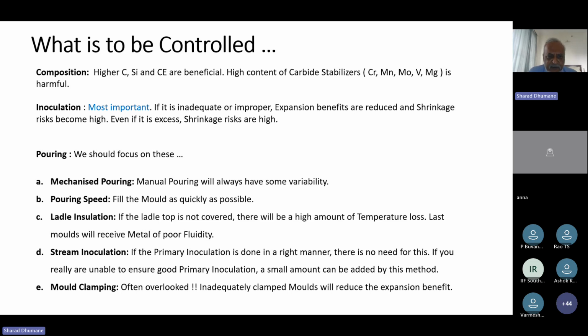Pouring speed: fill the mold as quickly as possible. If you are taking more time, then we are exposing the liquid metal. Imagine the metal is falling in air, and since it is at a higher temperature, it is attracting oxygen at a higher rate. So if you are pouring for a longer time than necessary, then you are increasing the liquid slag formation, the oxide formation. So pouring speed is another important parameter.